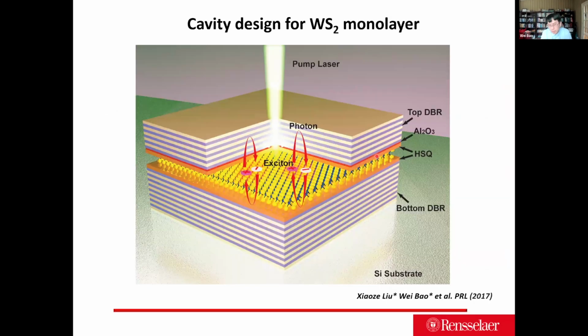So back in 2017, Xiaoze and I, who at that time still worked as postdocs at UC Berkeley, tried to overcome this 2D material fabrication issue by using e-beam resist, essentially a spin-coated polymer-like material. Once you thermally heat up this so-called HSQ, it converts into silicon dioxide. By spin coating HSQ, transferring the 2D material on top, and then spin coating another HSQ, we minimize the bombardment from thermal evaporation or e-beam evaporation on the two-dimensional material, and in this way minimize the sample degradation during fabrication.